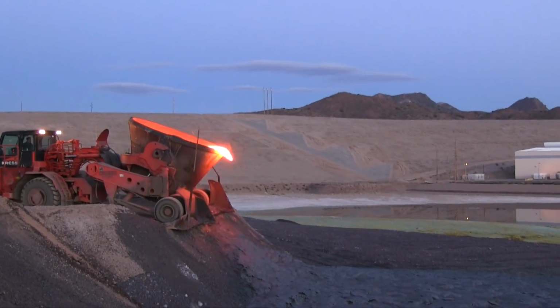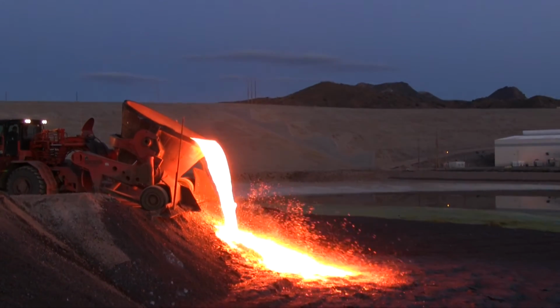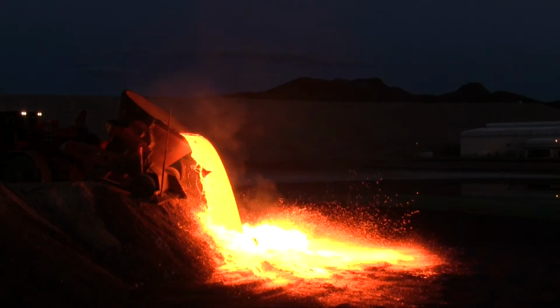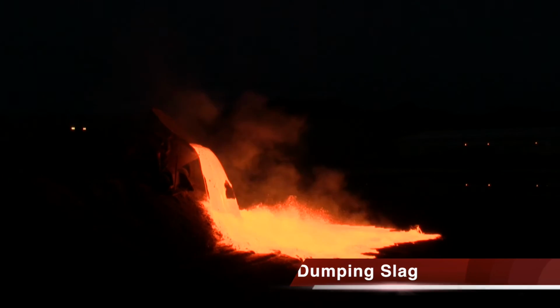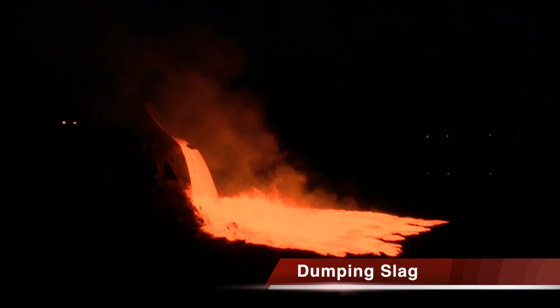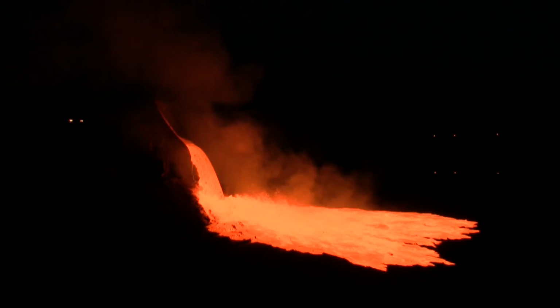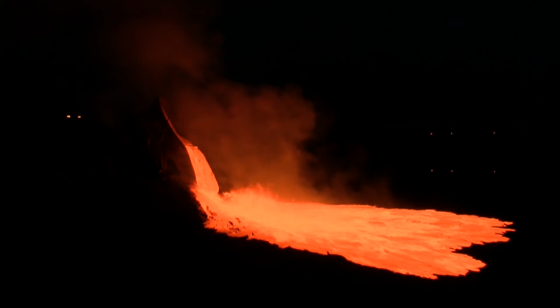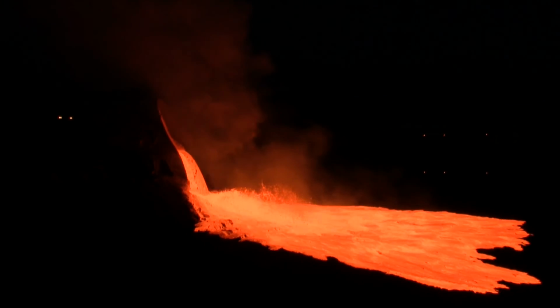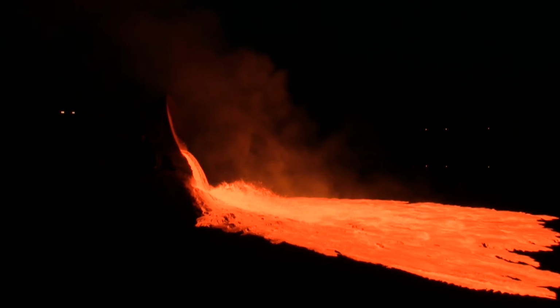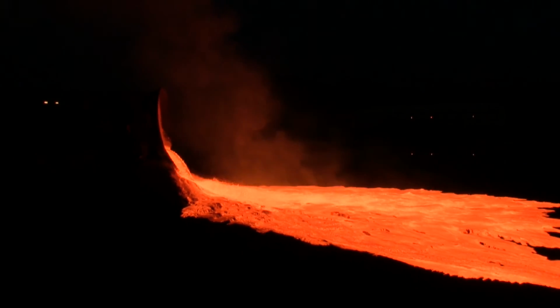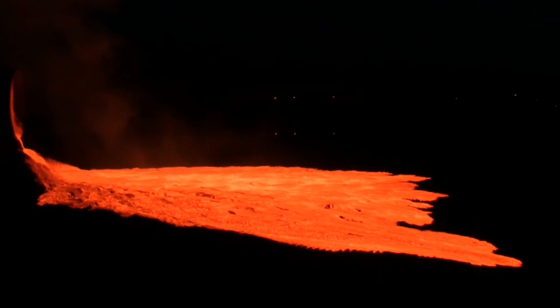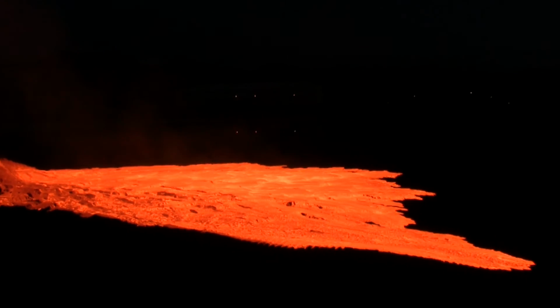The slag is the waste product that goes out to the dump. The copper content is 0.8% or less. On average, we send out 50 slag pots every day and they weigh 50 tons each. Our slag is inert because the glassy lava-like matrix encapsulates the minor impurities, preventing them from leaching into the groundwater. Watching the slag pots dump at night is a pretty exciting event as it lights up the surroundings.